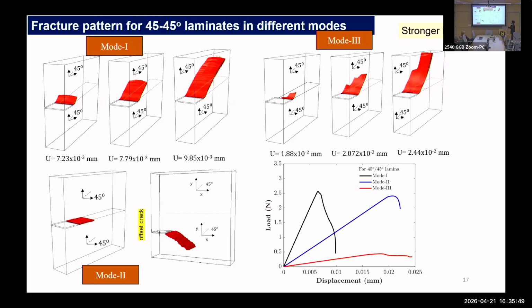Okay, so this is for other modes of fracture. So again, here the top and bottom fiber orientations are 45 degree. And what we are studying is how the crack will propagate under different modes. And here, this one is particularly interesting. This is mode 2, in-plane shear. What we saw is that the fracture path depends on where the pre-notch is. If the pre-notch is at the mid-plane, where the interface is, then we see pure delamination. If the pre-notch is at an offset with respect to the interface, then we see an inclined crack propagation, almost as if it doesn't even realize the presence of the fiber. So if it was pure matrix-driven crack propagation, you would have seen a crack path like this.